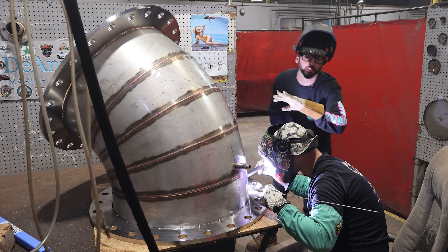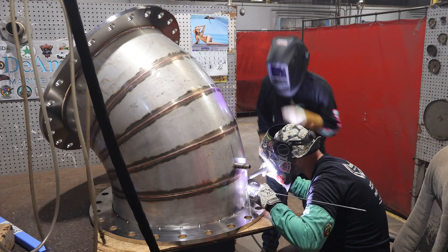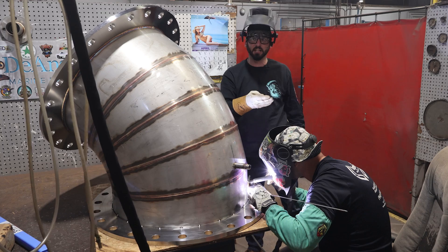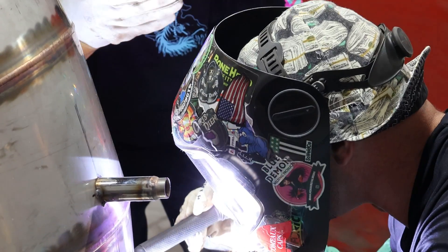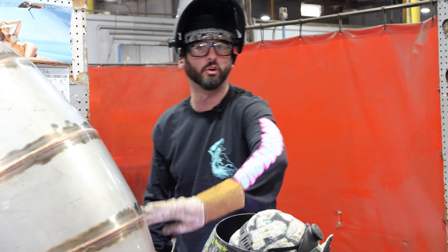You're at four seconds, you're falling behind. Patience — slow and steady wins this race. When it comes to stainless, there is a bit of a trick to it. Given it's so thin on that higher part — you said it was 12 gauge — and you're welding it to something that's like three quarters of an inch thick. Yeah, and it's 347 filler. What does the 347 have to do with it? It has a lot of chromium and nickel in it, which is better for heat resistance and salt corrosion. Some of that good austenitic stuff. Yeah, she likes to burn a little dirty and a little slower than regular 316. I always say it welds like pudding. We're at 150 amps, a minute and 15 seconds, and we've made it a whole four inches so far.